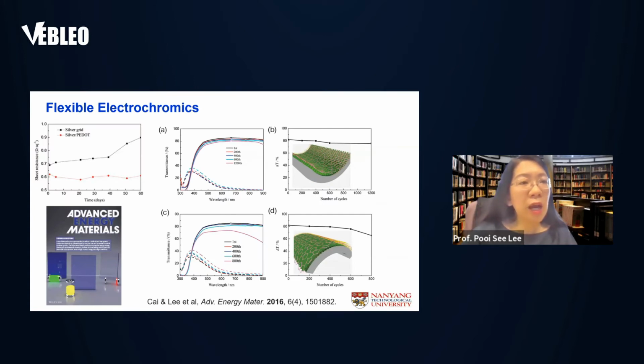So as we can see here in the sheet resistance measurement as a function of time, or number of days, upon passivating with a top PEDOT layer, the conductivity can be maintained over a couple of months, whereas without the PEDOT, the silver grid might undergo oxidative degradation. And after making the transparent conductor, we print the tungsten oxide onto the layer and fabricate the device in order to demonstrate the transmittance modulation upon application of a small potential.